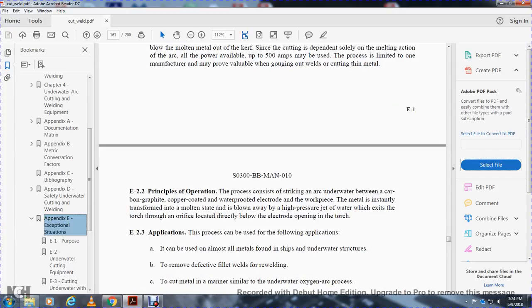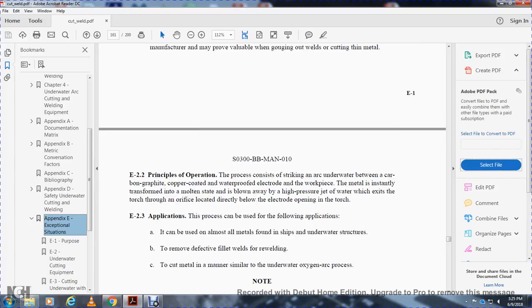Alright, E2.2, principle of operation. The process consists of striking an arc between a carbon graphite, copper-coated, waterproof electrode and the workpiece. The metal is instantly transformed to a molten state and blown away by a high pressure jet of water, which exits from the torch outlet located directly below the electrode opening in the torch.